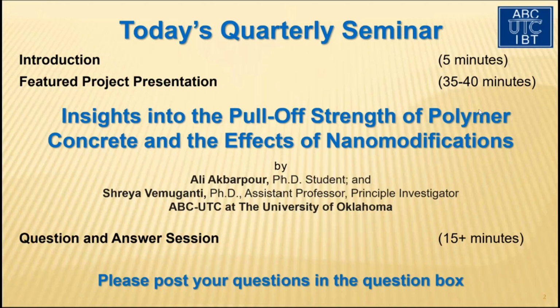But after mixing, the CNTs have no flying nature because they are already in the resin. And if it's functionalized carbon nanotubes, they are potentially making a chemical bond with the resin itself. So after mixing, no potential risk. Before mixing, PPE needs to be used to prevent any kinds of aerosols getting into respiratory systems. Okay.